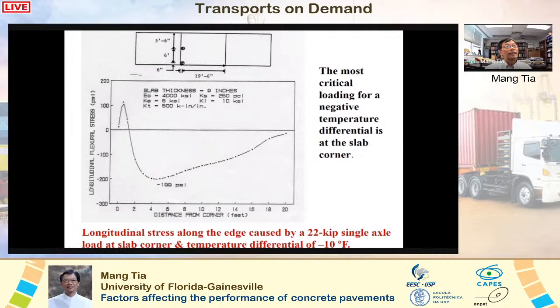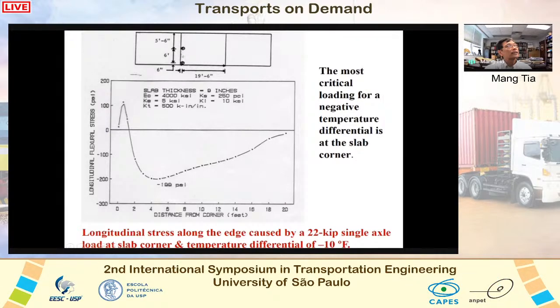Analysis was made to determine the most critical loading condition at night. At night, where would we place the load so that we get the maximum stress? And what we found is that at night, when the slabs tend to curl up at the edges, the most critical loading condition is when we place the load at the corner, as shown here. It shows an axle load with two loads, for one axle. If the load is applied here, when we have a negative temperature differential, we're going to get the maximum stress.